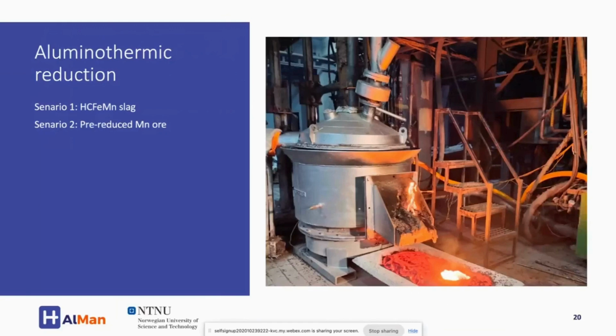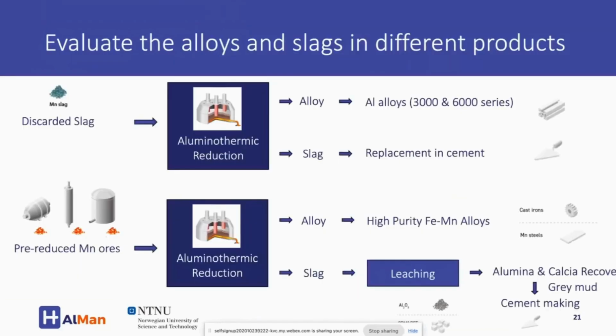And then the smelting. We have 3 different scenarios that we will demonstrate. The first 2 scenarios have already been done. So here what we have done is that we took ferromanganese slag that's discarded today and put it in as a raw material, and then we just reduced it further with aluminium, and that was the first campaign. The second campaign was that we used pre-reduced ore and reduced it with aluminium. And then if you click one more, we will do a third campaign now where we're going to use pre-reduced ore again.